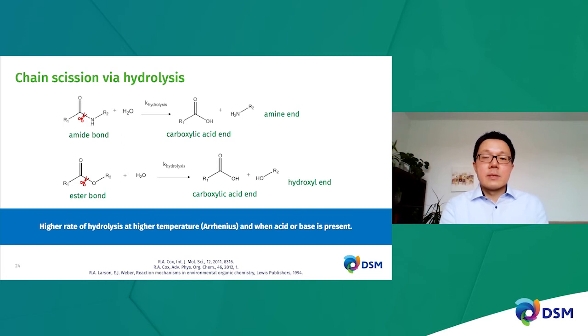When we are talking about polymer degradation, the most well-known degradation mechanism is hydrolysis. In this case, I show two different reactions. The first one is the reaction between polyamide and water. When water starts to react with amide bonds, the amide bonds are cut, or cleaved, to form carboxylic acid end groups as well as amine end groups.